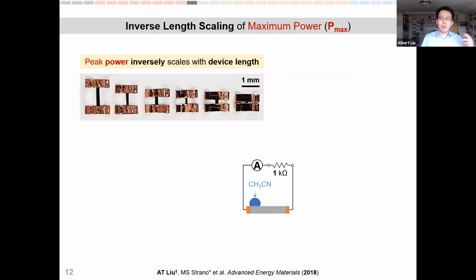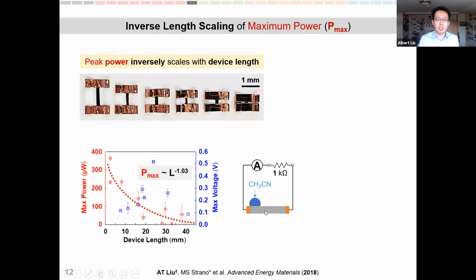We're also wondering about the power production performance of asymmetric chemical doping. So in order to test that, we do closed circuit current production measurement for asymmetric chemical doping. And we saw that as a function of decreasing device length, actually we get an increase in maximum power production. This may be odd at first glance, but it actually isn't, because our device has smaller and smaller internal resistance as the device length decreases. As a result, you generate more and more current given the same voltage.